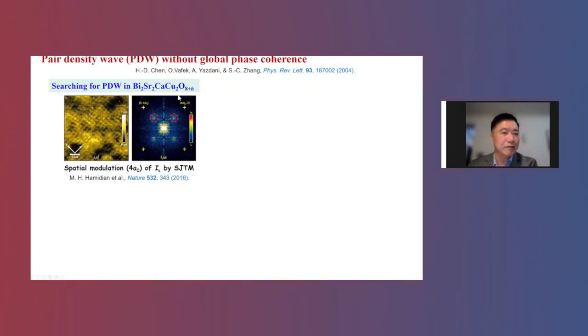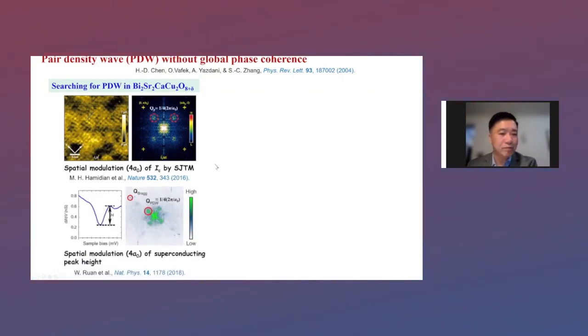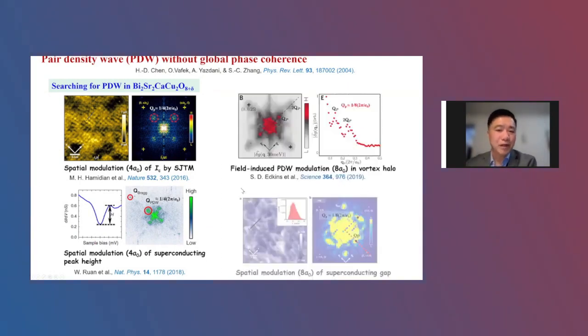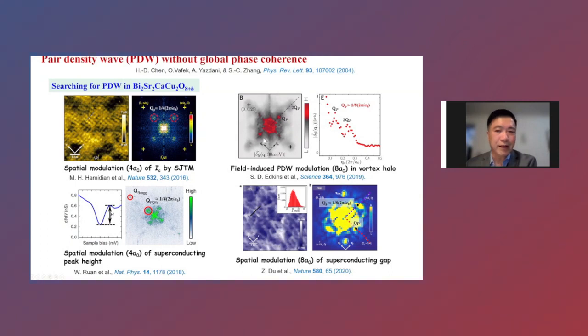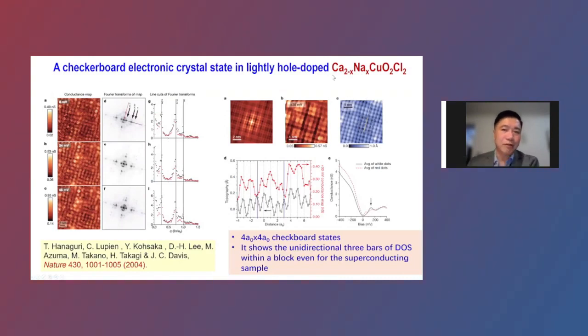About the pairing density waves, there are a lot of studies from Seamus Davis's group and from Yao Wang's group, okay? So either 4a or 8a, some measurement. And also even in the superconducting sample of this CCOC, you can see that for the superconducting sample, Hanaguri-san and Seamus Davis's group by that time also saw this kind of 4a by 4a plaquette. And within that, they also see this 3/4, okay? And if you blow it up, you can also see some kind of 3 bars of density state that corresponds to this 3/4.